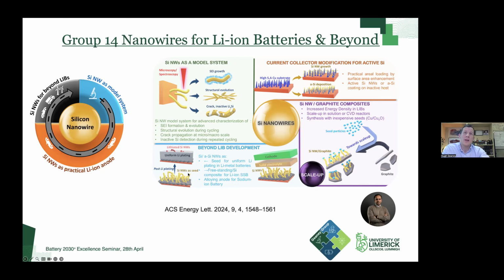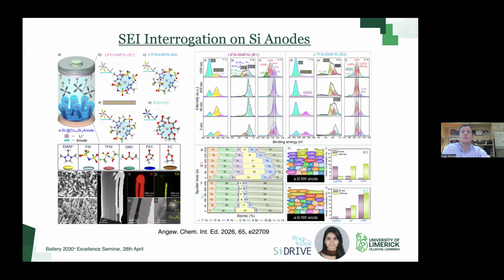In terms of beyond lithium-ion development, this is the work that I'll show in nice depth, is around using the fact that these materials are lithophilic to try and guide lithium plating and stripping within metal anode systems. One of the model system type papers that was published, so this was carried out by Abhinaya Sankaran. This was within a Horizon 2020 project, which is finished, called SiDRIVE. It's the first of the two Horizon type projects that were coordinated by Professor Kevin Ryan here in the University of Limerick.